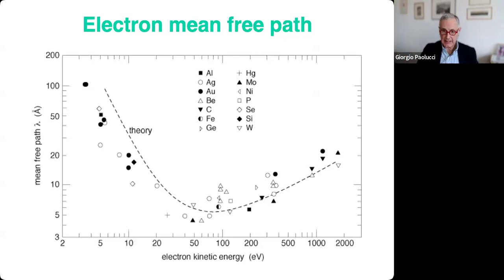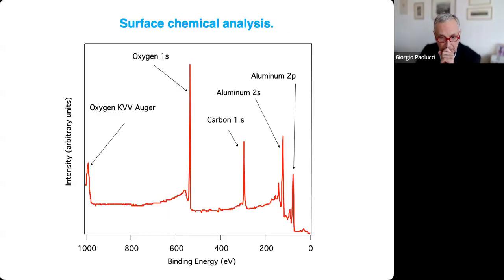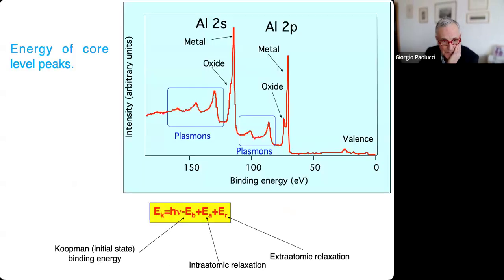Okay, if you zoom on that spectrum, if you look at the zone around the aluminium 2p and 2s, you see that there are various components. One can be associated with the metal, and one is associated with the oxide, and that is what I was saying before, that you can actually distinguish the oxidation state. Because why is that? If you imagine you form an oxide, what happens is that you're transferring electrons from the metal to oxygen, and because of that, there are fewer electrons on the metal site, and the energy shifts to higher binding energy. So normally the oxide has a higher binding energy than the metal.